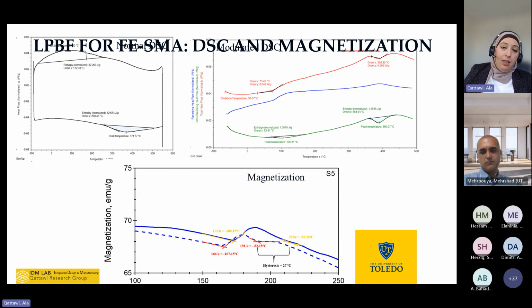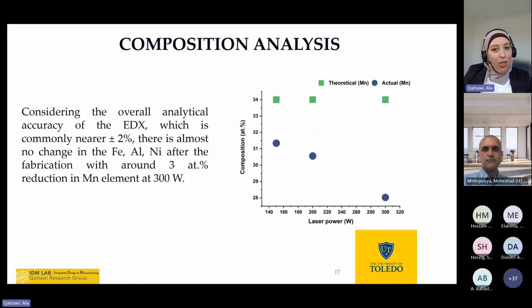And then the next idea in this analysis, when we understand additive manufacturing, is material evaporation. So if we look at the composition analysis of the material, specifically for the low melting point of manganese in this alloy system, you can see that when we increase the laser power, tentatively we will have a reduction in manganese. So there's a manganese percentage that actually evaporates during the print. So although we put the same alloy composition as the traditional one, we have a 3% reduction in the manganese if we increase the temperature or the laser power.